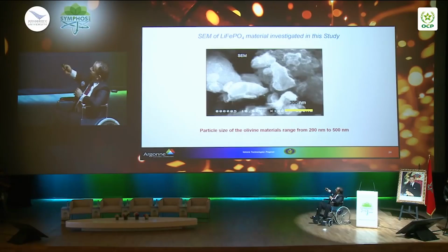Here we have a particle that is 300 nanometers that gives you fairly good performance, because the pathway of lithium diffusion has been shortened. So it's much easier to move lithium out than if you have a micron-size particle like in the oxide, where the density plays a very good role in energy. But unfortunately here, if you use nanomaterial, your density is very, very low. You can't pack active material in the electrode and therefore in the cell. So that's a challenge for the iron phosphate. Because if you have low energy, you have to put in more cells, and that increases the cost of the full pack.